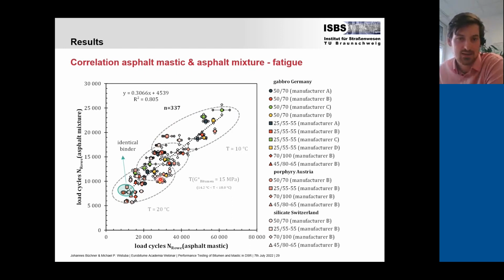Here you can see again this iso-modulus temperatures. It's in the intermediate range, 14 to 18 degrees C for each of the binders, kind of overlapping both of those here, but still again with the differentiation between different materials, we can see which materials have the highest resistance to fatigue cracking, so to say, and materials with lower resistance. We see again that softer materials, the 70/100 here, have the lowest resistance, the lowest load cycles. So again, a clear differentiation and characterization is possible, and also a correlation between both scales, which we are looking at.